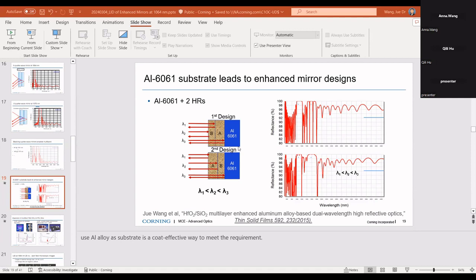Here is an example. On the left is a perfect multilayer structure. On the right is a half micron defect seed supposed to sit on the substrate surface, and then how the cone forms. This is just a geometric simulation. And then we can see, when you irradiate with a 1064 nanometer laser, how the field strengths distribute. You can see that actually it's focused deeper into the aluminum substrate.